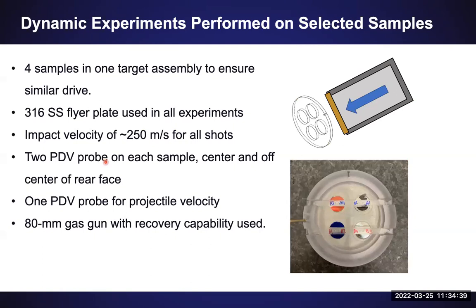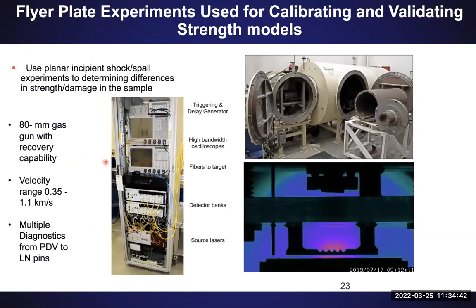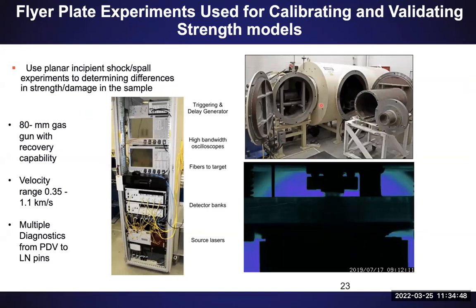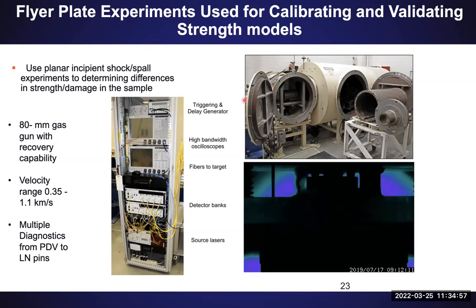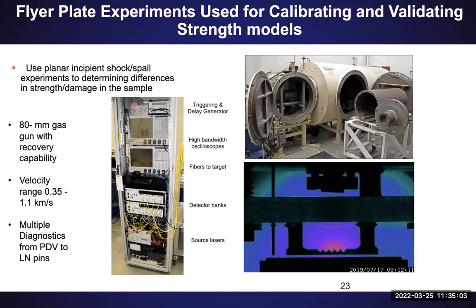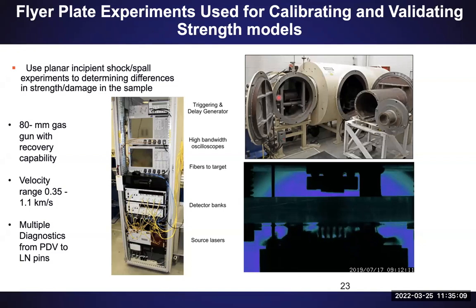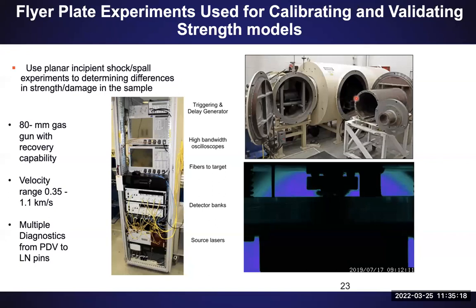We take these materials and we can perform dynamic testing in our laboratory. So basically on the top right, I'm showing a chamber where this is where my laser pointer is, where we actually put in our target. There's a gas barrel, a gun barrel that you can't see in this picture, but it is about 80 millimeters in diameter. We put our targets in there, and a cool thing that we do that's unique in the world, I would say, is we actually recover the samples after they are impacted by a projectile. So they get recovered in this small tank that goes into this larger tank.